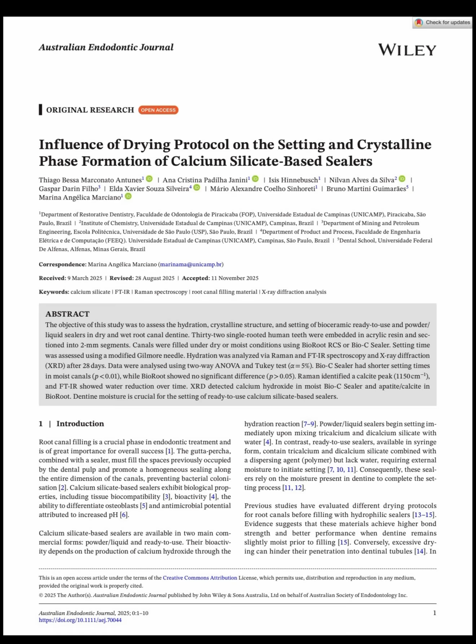Endodontic treatment depends on a homogeneous seal that prevents bacterial colonization, and calcium silicate-based sealers are favored for their bioactivity and biocompatibility, but their performance depends on a hydration reaction that produces calcium hydroxide. These sealers exist in two forms: ready to use, which contain no water and rely entirely on external moisture from dentin to initiate setting, and powder and liquid, which begins setting immediately upon mixing as they contain internal water.